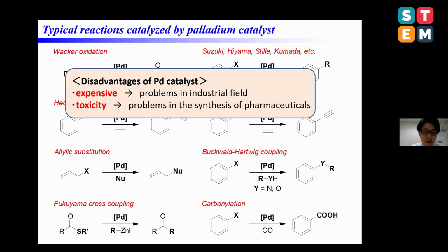However, despite these achievements, palladium as a catalyst has two main drawbacks. One is palladium is expensive, and the other is the toxicity of palladium. The cost of a palladium catalyst can represent a large proportion of the total cost of performing a reaction. The toxicity of palladium leads to problems in contamination of the final product, which is why cross-coupling reactions are normally not used in the final steps of a drug synthesis. Conventional reaction conditions involve catalyst loadings of several mol %, which are far too high for practical use in the chemical industry.